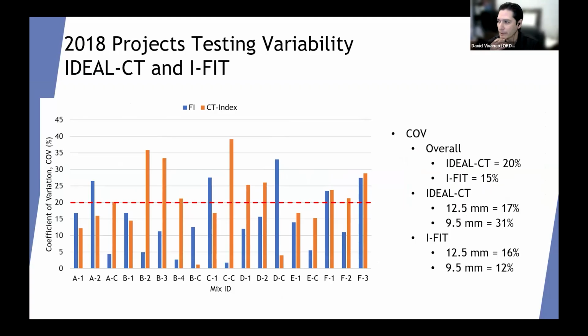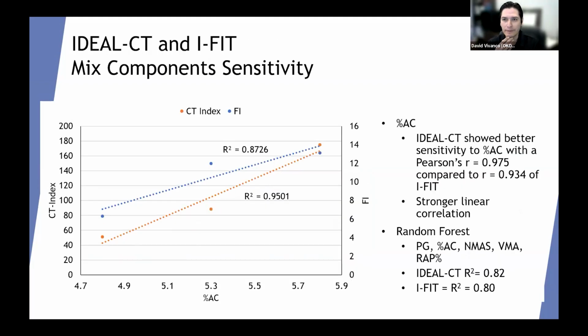And then when we go by nominal maximum size on the 12.5 millimeter mixes, they show very similar results with 17 and 16% COVs. And then we also checked sensitivity to mix components, specifically asphalt content. So we ran 3 different asphalt contents on each test on lab fabricated specimens, and we observed that IDEAL-CT had better correlation with R-square of 0.95. So that told us, okay, IDEAL-CT is telling us a bit more in terms of asphalt content.